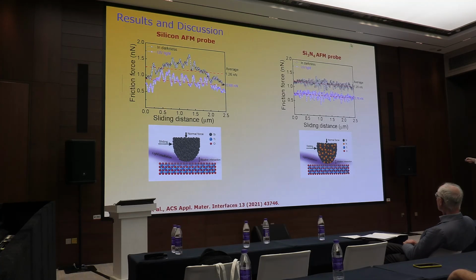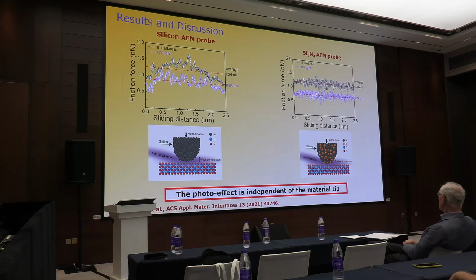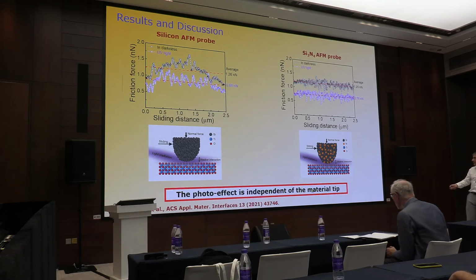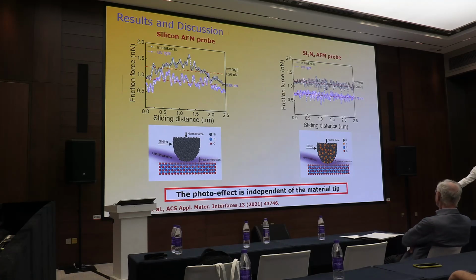In both cases, black is darkness and violet is UV. Using silicon or silicon nitride, the friction force is lower when we use UV. Here you can see the silicon tip and the silicon nitride tip. In both cases, when we use UV, the friction is reduced. What is the most important result or conclusion here? The photo effect is independent of the material. We use silicon or silicon nitride, and in both cases we see the same effect, a reduction of friction.